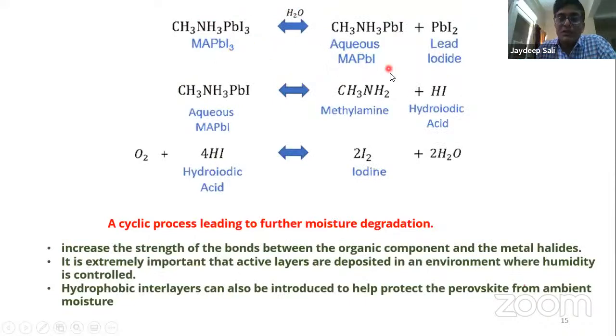So here are certain chemical reactions which have been identified, which can be the cause of degradation of the perovskite phase. As you can see here, initially we have CH3NH3PbI3, MAPbI3, as the perovskite structure. When it reacts with H2O, through successive reactions, ultimately you can see that it can separate the iodine from the compound, and it can also create water molecules. So it can be looked at as a cyclic process, because in the presence of H2O, it not only degrades the original material, but it also creates additional water molecules, which cause further degradation. If such a thing happens, then the performance of the photoactive layer is definitely degraded.